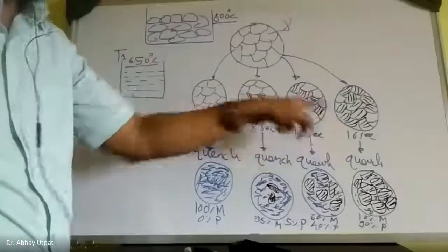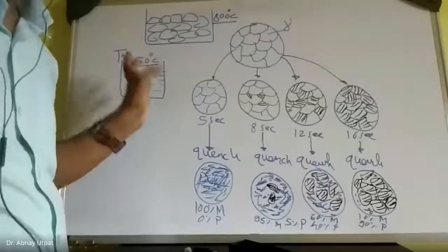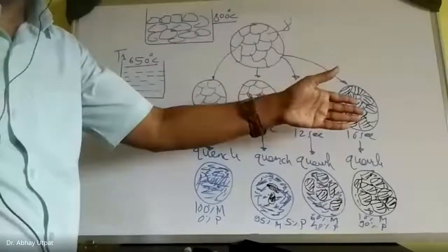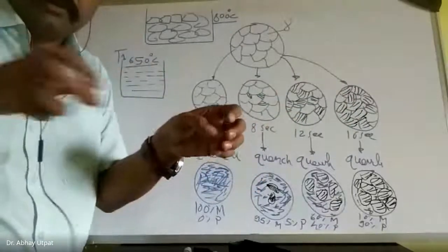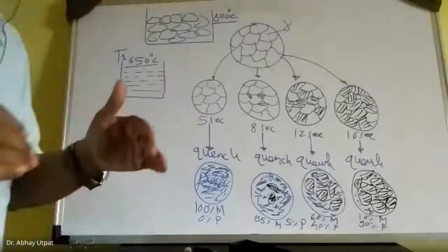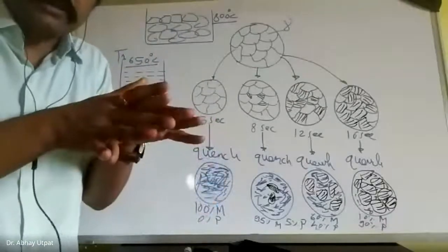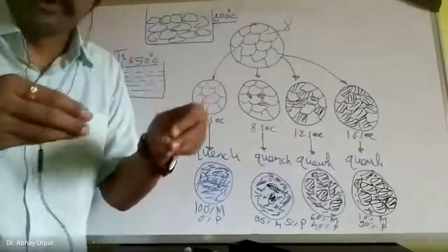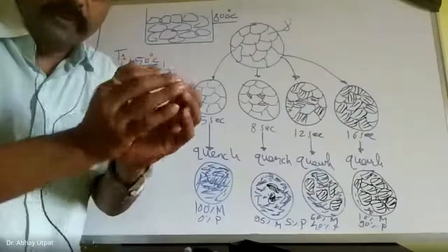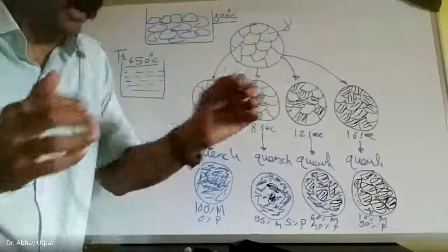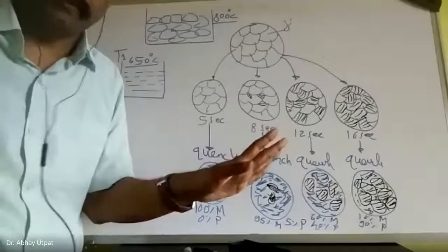and hold in the bath of 650 degrees Celsius, where after 16 seconds there is sufficient time, so atoms of FCC structure will move now because they are not stable below 727. As soon as they come below 727, FCC structure gets disturbed and atoms will start moving, and they will rearrange themselves into a mixture of BCC plus orthorhombic, and almost 90% structure is produced in 16 seconds. But still I didn't give time for completion.